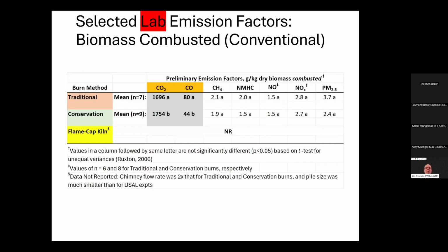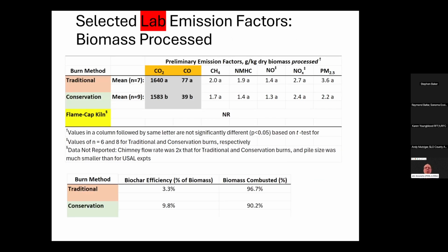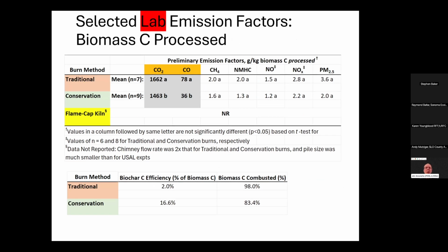So again, going back to lab emission factors, we have conventional numbers, and performing this statistical analysis, we see both CO2 and carbon monoxide are significantly different. They're different from each other. Whereas none of the other parameters of this major set of parameters showed a difference. We go to the biomass processed, where we have biochar efficiency of 3% for the traditional and about 10% for the conservation burn, and it sharpens those differences a little bit more. And then when we go to the biomass carbon processed, again, just CO2 and carbon monoxide are the only two that really showed differences, whichever emission factor we went with.